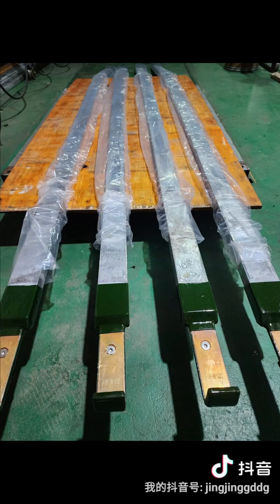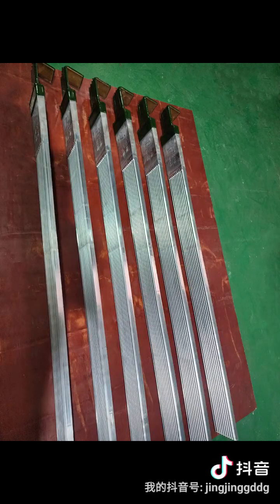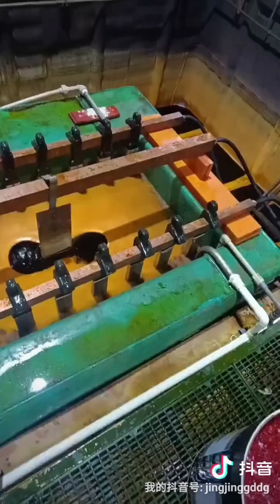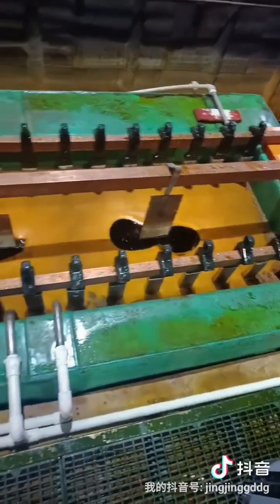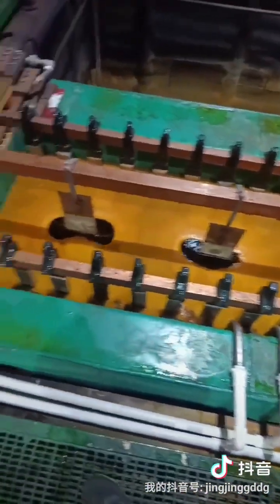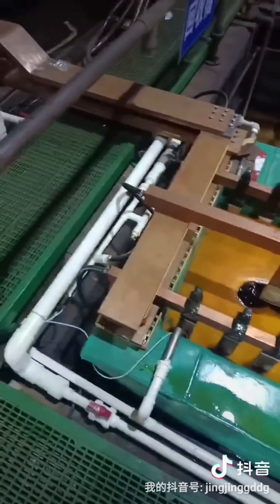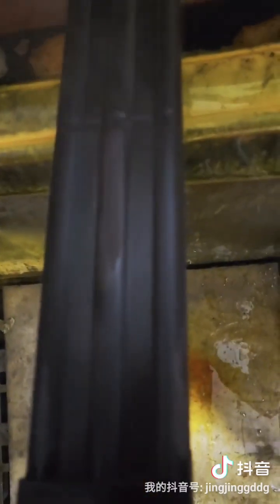In the absence of electricity, the lead alloy anode in the chromium plating solution forms a yellow lead chromate, PbCrO4, film with poor conductivity on its surface due to corrosion by chromic acid, which increases the slot voltage and even causes the anode to become non-conductive, seriously affecting the quality of the workpiece coating. Therefore, when not in production, the anode should be promptly lifted out, washed clean, and immersed in a clean water tank.